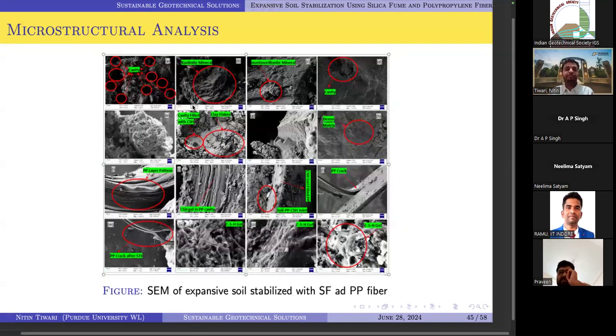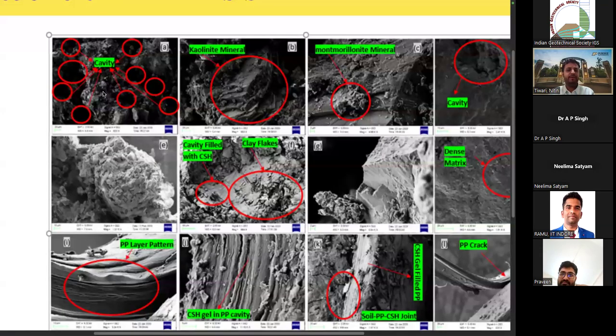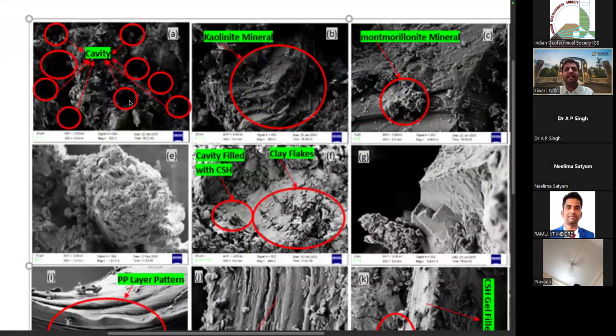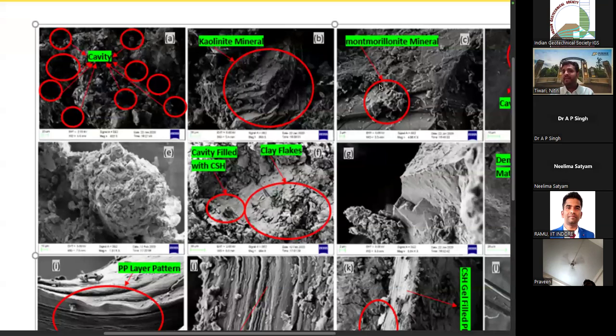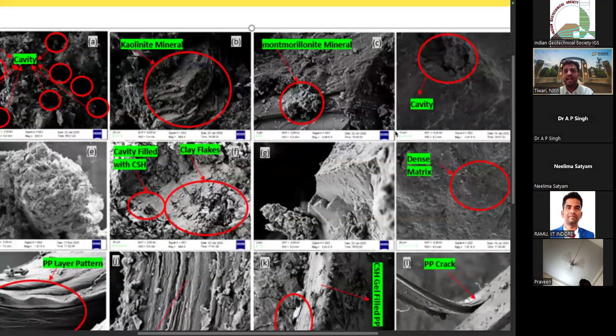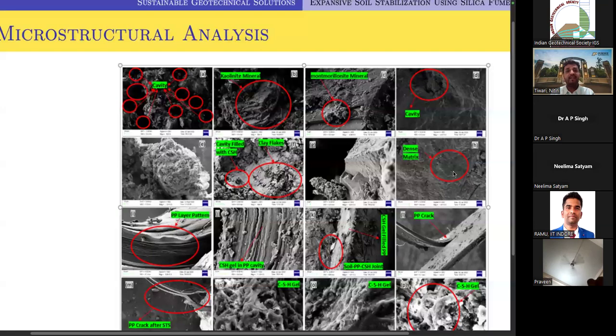Coming to the SEM analysis, this is very important. I'll just enlarge a little bit for you. So you can see initially we had a lot of cavities inside the samples. Exactly, you can see kaolinite mineral and montmorillonite mineral were observed inside. You can see a lot of cavities here. But with the treatment, you can see clay flakes filled with CSH gel, this completely layered clay particle you can see. At the same time, initially we had cavities, but now we are observing a dense matrix.